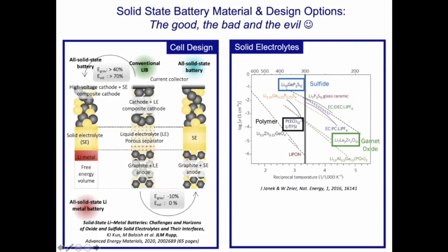On the right side, you can see an Arrhenius diagram where you have on the y-axis the log of conductivity for the lithium, and on the x-axis you have the reciprocal temperature. Now, if we look into that, there are two major classes that compete with today's polymer separators that you find in a classic lithium-ion battery. There are the oxide classes, where you can find materials like so-called lithium garnets, and there are the sulfide classes, where you can find materials like LGPS and others. They have quite high conductivities that are within one order of magnitude comparable to today's liquid electrolyte porous separators. However, they are now in a solid state form.